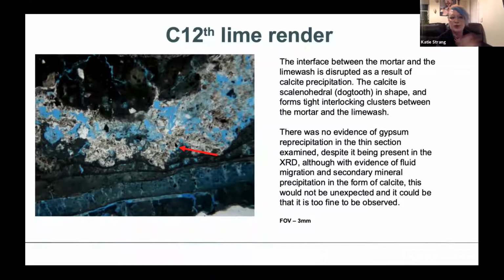Essentially, when you've got moisture moving through your material, you're dissolving some of that calcium carbonate, and then it gets redistributed and deposited elsewhere, normally within pore spaces. And essentially what this was doing was creating an impermeable barrier between your outer surface and your internal mortar, which was causing a lot of the front surface to flake off. And you can't actually see the gypsum in this thin section. You need to do it at higher magnification. Quite often the gypsum is interspersed with the calcite and it's very, very fine.